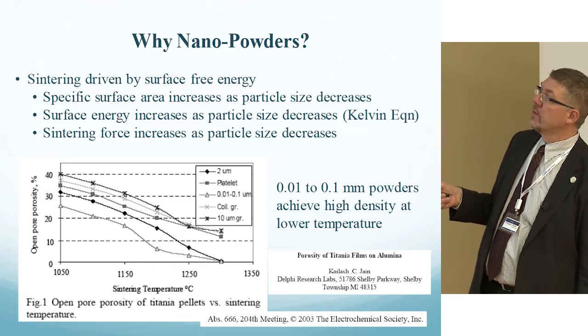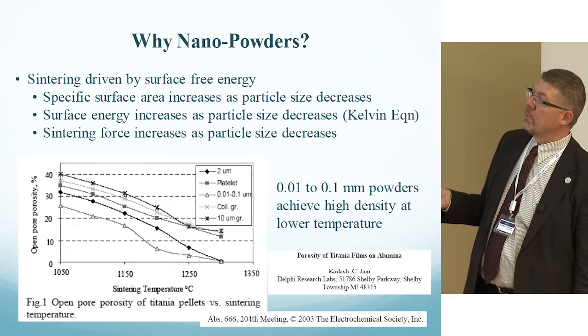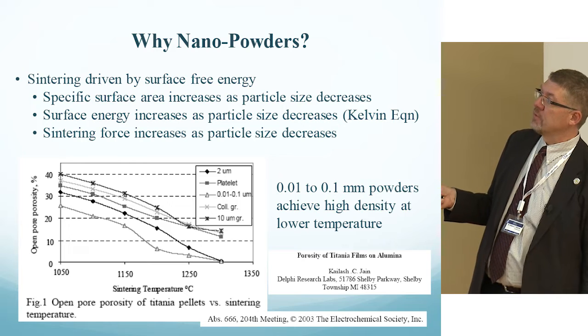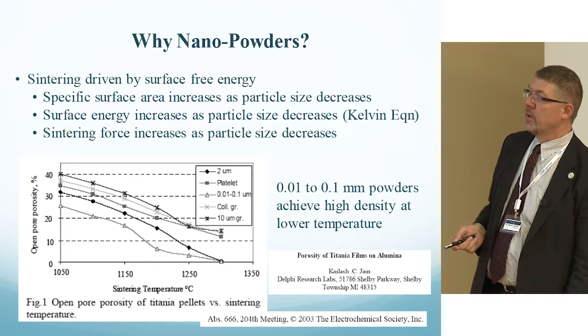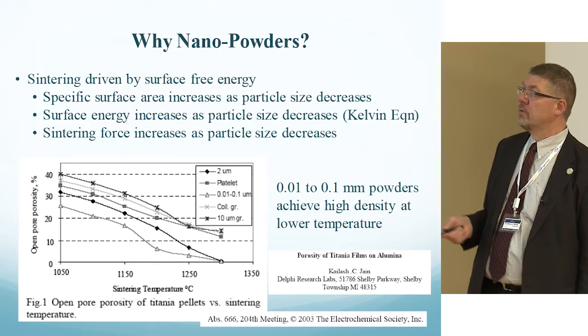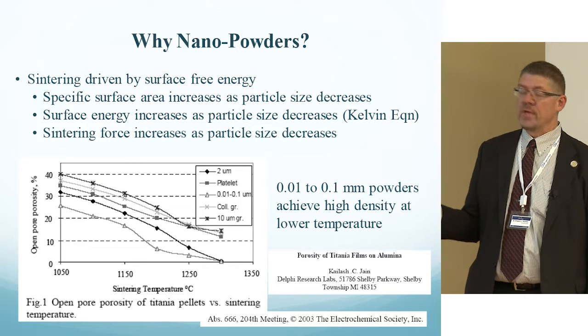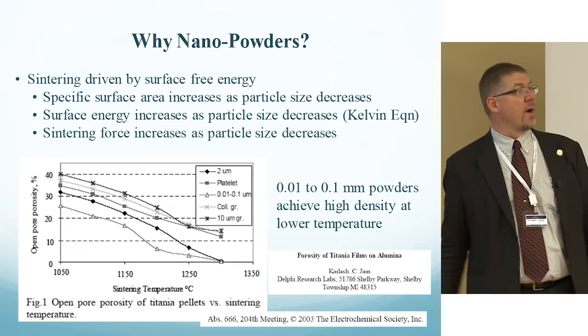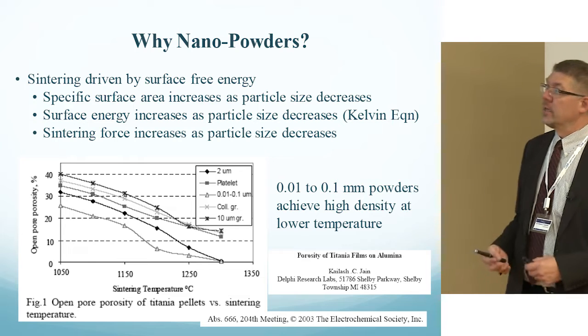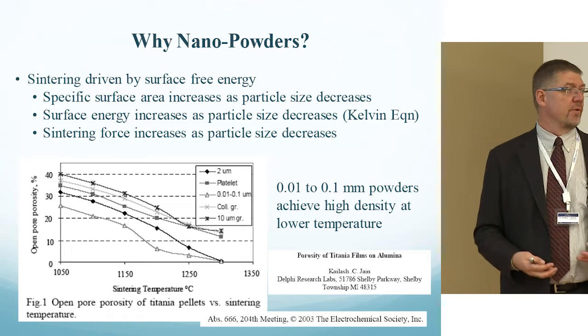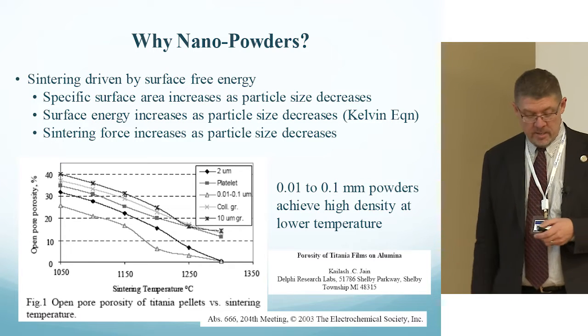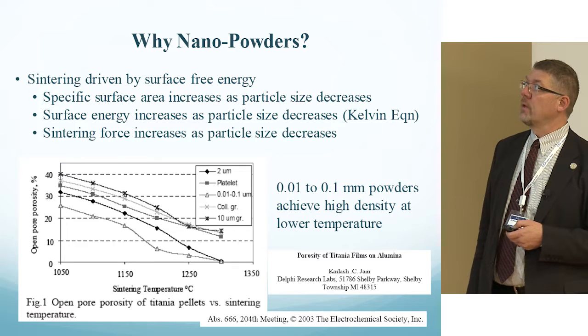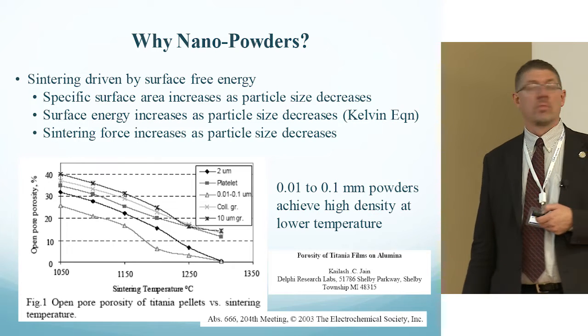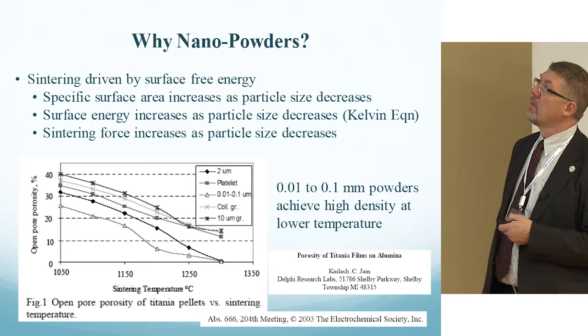And as you can see here, as you get the open pore porosity, it starts to drop down to essentially zero between 1250 and 1350 on titania. So there have been studies done with this on YAG and other materials, and you see the same drop off on the curve. So getting it to the right size, driving the free energy, using the thermal mass of the heater, you can make nice material with these nanopowders.